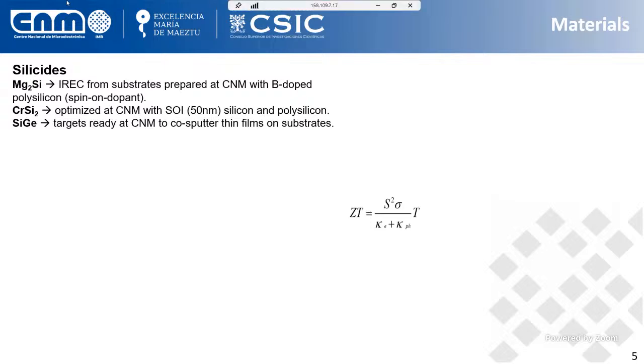The magnesium part, at least, is not being carried by us, because magnesium actually turns out to be a very harmful, complicated material to manipulate in the clean room. So it's actually developed by IREC on substrates that we prepare, and then they come back to us in the form of the silicide of magnesium, and chromium silicide is being developed here by us through different RTA processes I will mention later. And we're also ready to integrate silicon germanium, because we have targets already available, and we are waiting to try to co-sputter them in thin film form on substrates that we have been developing. The silicides have already good Seebeck coefficients and good electrical conductivity, but we're trying to reduce the thermal conductivity by nanostructuring them.